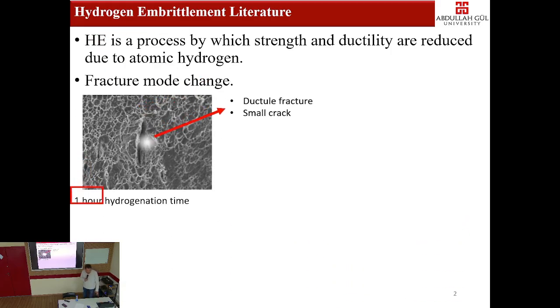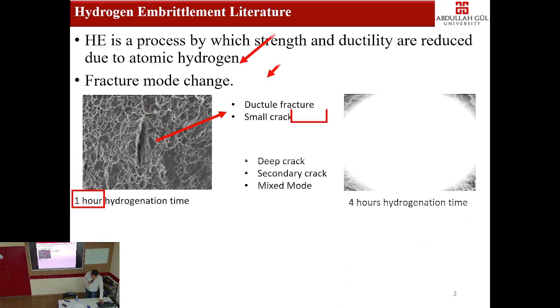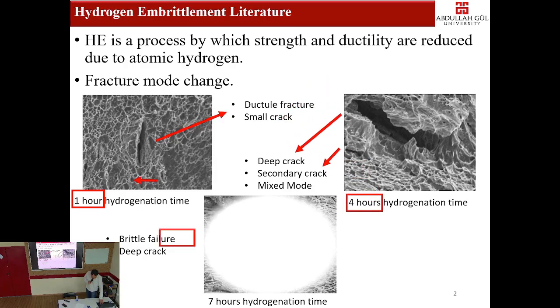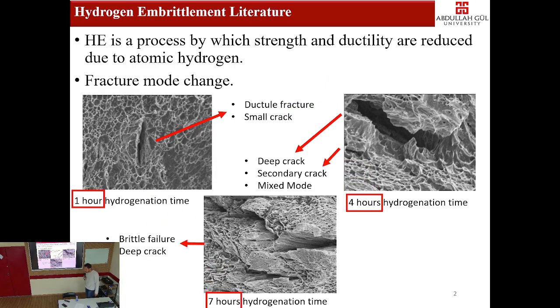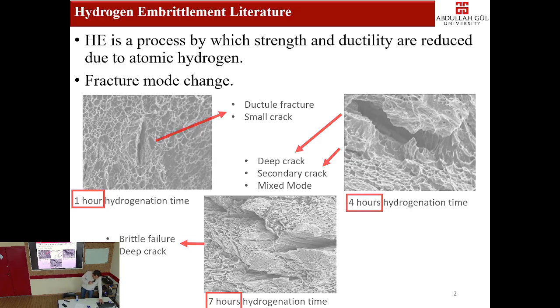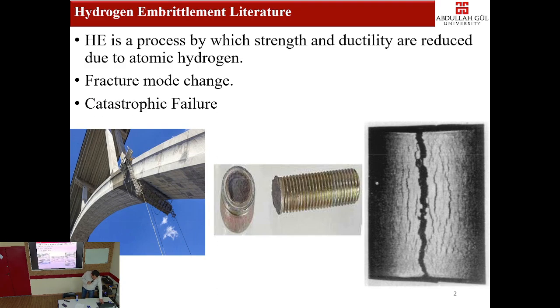Hydrogen changes the failure mode from ductile to brittle after even 7 hours of hydrogenation. These are the same materials. The only difference is atomic hydrogen. We have a steel, and it becomes like a glass. It's due just to some amount of atomic hydrogen, and it causes catastrophic failure.